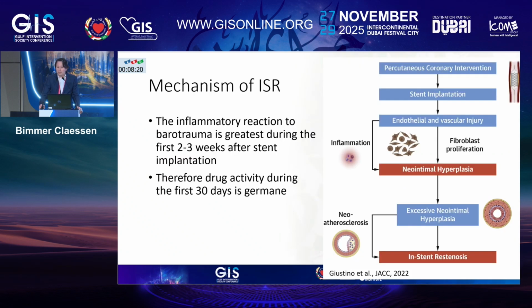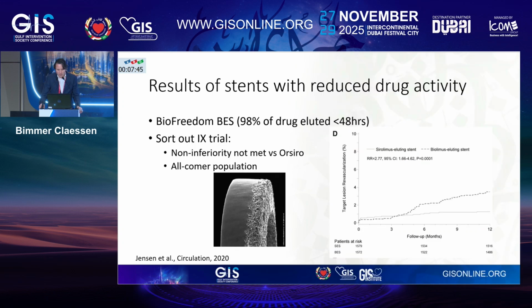Because when we look at the mechanisms of in-stent restenosis, we know that the inflammatory reaction to the barotrauma that we induce when we inflate a stent is the greatest during the first 2 to 3 weeks after stent implantation. This barotrauma leads to endothelial and vascular injury, which leads to fibroblast proliferation, and that leads then to neointimal hyperplasia. So the drug activity during this early phase after stent implantation is of the utmost importance. You'd need the drug to be effective for a couple of weeks in order to have adequate suppression of this restenosis phenomenon.